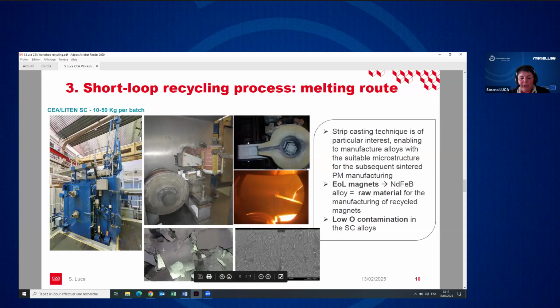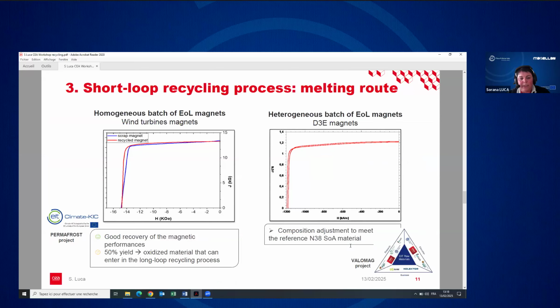You can see in this picture an example of recycled alloy in the form of flakes with the particular microstructure that I told you before, which is formed by magnetic dendrites of the magnetic phase, separated by a very thin rare earth rich phase. And this particular microstructure is very useful for the next step of the manufacturing of the magnets by the powder metallurgy route.